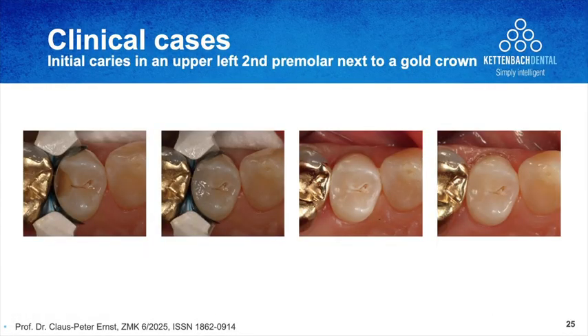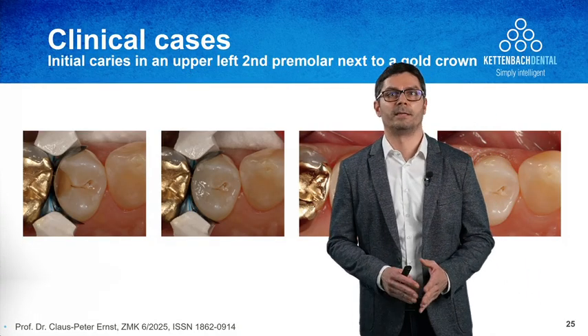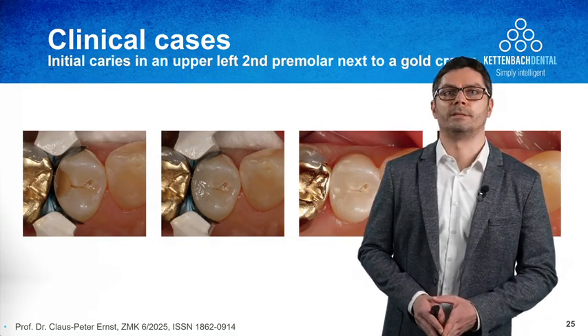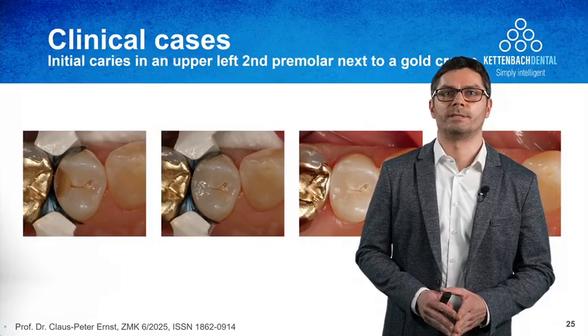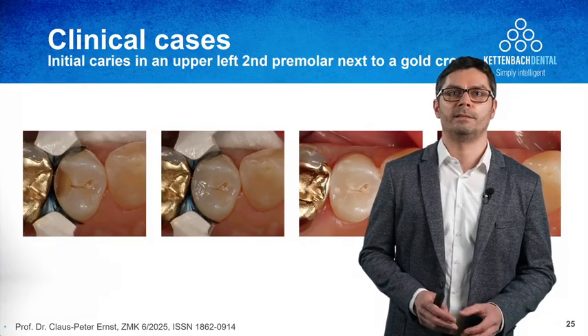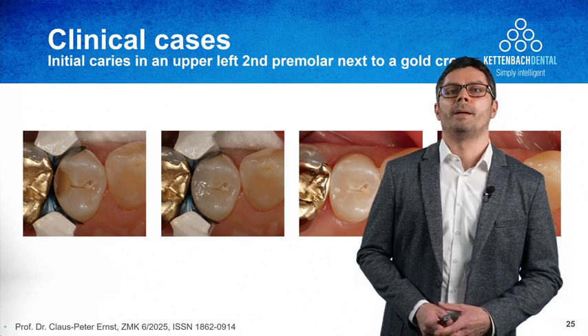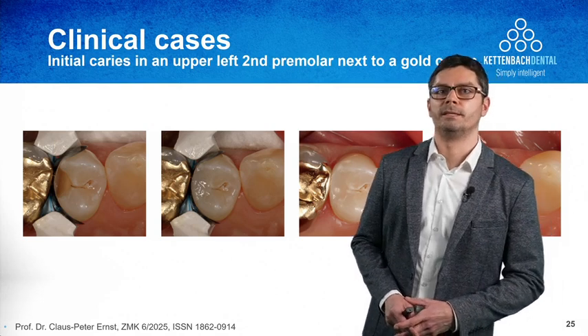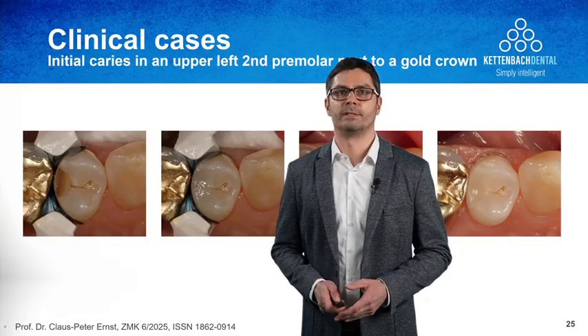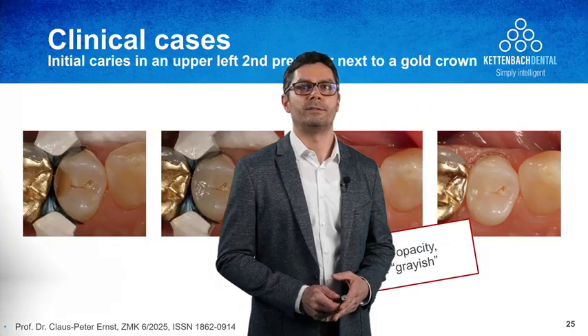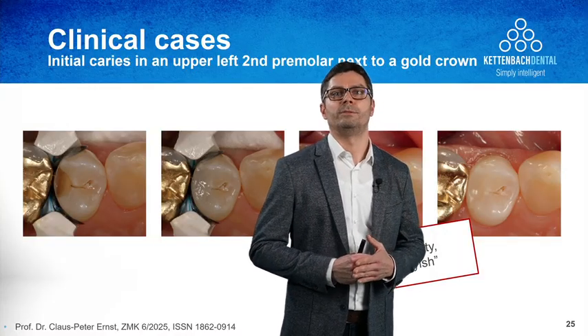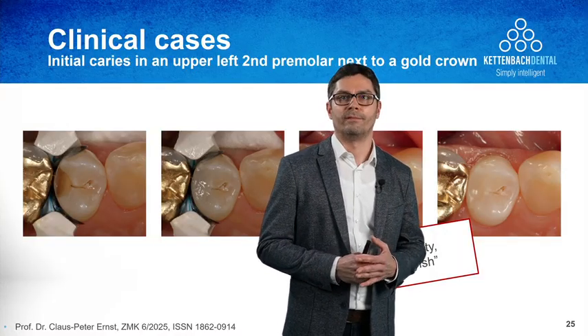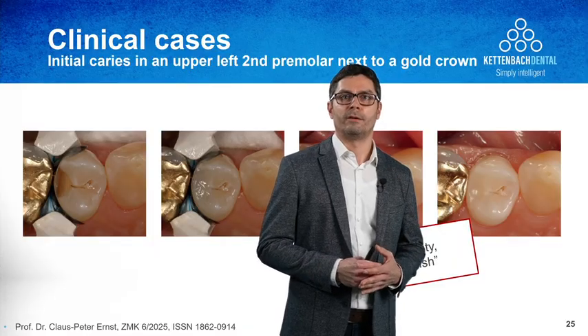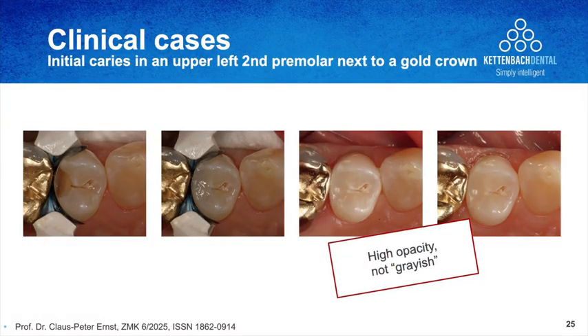Here we have another case where the restoration was placed next to a gold crown. As you might know, if placing restoration materials, especially bulk flow or bulk materials in general, beside a restoration that is very high in opacity or very high in color, in some cases you can see a grayish appearance of the resulting restoration. As you can see here, we do have a nice result even placed in contact with the gold restoration, so it doesn't look grayish or anything like that. So once again, a very nice result for the appearance of the material due to the higher opacity, so you cannot see the restoration next to it.